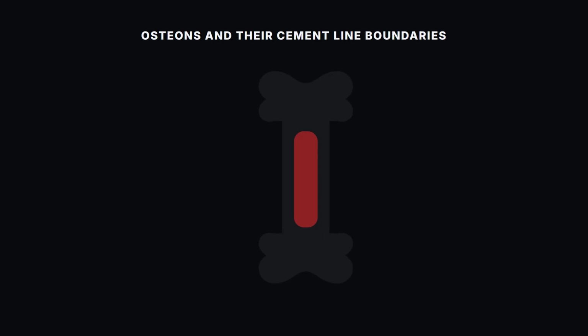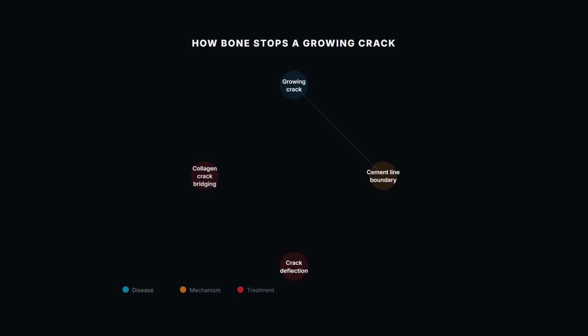Researchers, notably materials scientist Robert Ritchie's lab, identified two dominant mechanisms bone uses to resist crack growth. Crack deflection happens when a growing crack hits one of those cement lines and gets redirected sideways instead of punching straight through. Crack bridging happens when tough collagen fibrils span across a crack's open faces, physically holding the two sides together and resisting further opening.